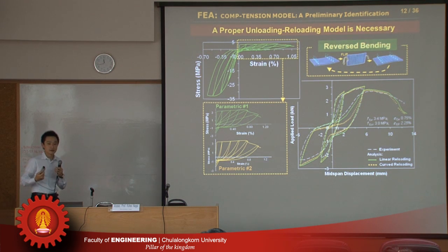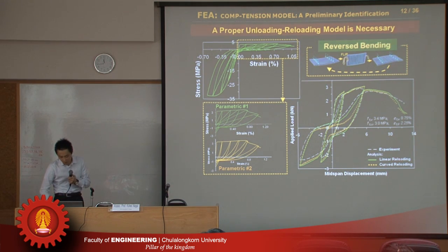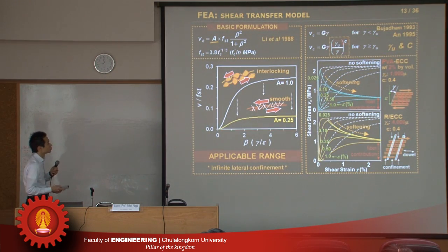And then we did the simulation by FEM, where we install the newly developed model, and we check the two cases where the reloading curve is just straight or curved shape. The white one is the experimental result of this reversed bending test, and we found that the green one is better, meaning the straight curve gives a better result. So then we adapt this model for the unloading and reloading curves. Then after that, yes, we move on to the shear.